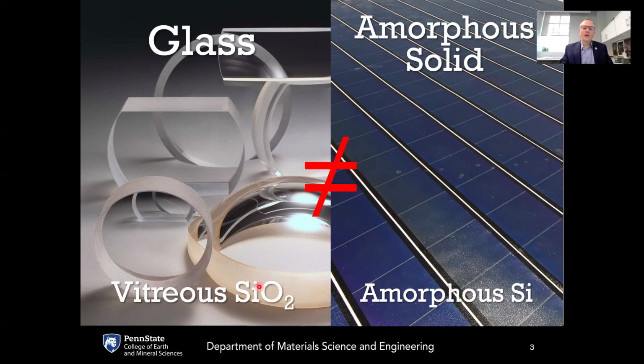One of the main differences is that the structure of glass, such as vitreous silica, is frozen in from the structure of its corresponding liquid. So the structure of silica glass is very similar to the structure of silica liquid. Each silicon here is fourfold coordinated. It is bonded to four different oxygen atoms. Each oxygen is bonded to two silicons. And so the structure that the glass has is inherited from the liquid state. An amorphous solid, on the other hand, also has a non-crystalline structure, meaning that it is lacking the periodicity of crystals. However, the structure of an amorphous solid is different than that of the corresponding liquid.